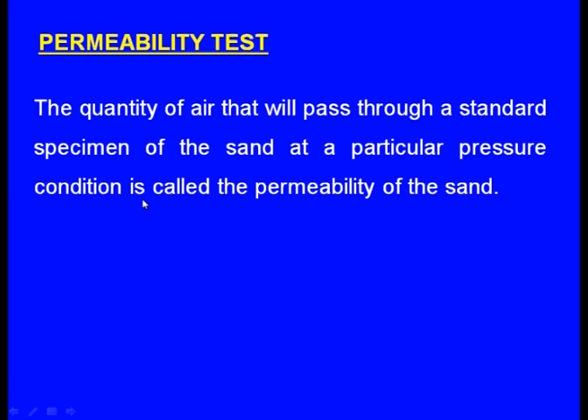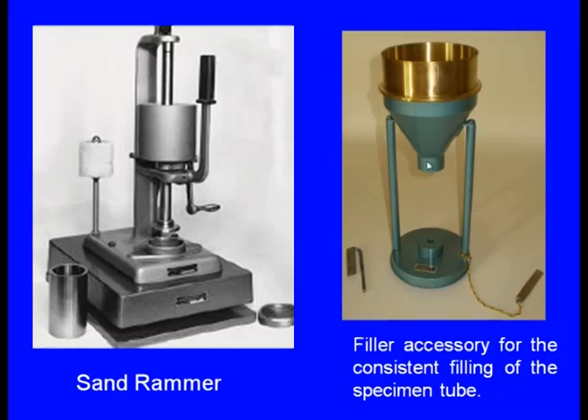The quantity of air that will pass through a standard specimen of sand at a particular pressure condition is called the permeability of the sand. We make a sand specimen — generally 2 inches diameter and 2 inches height — and measure how much air passes at a particular pressure. For that purpose we use the sand rammer.